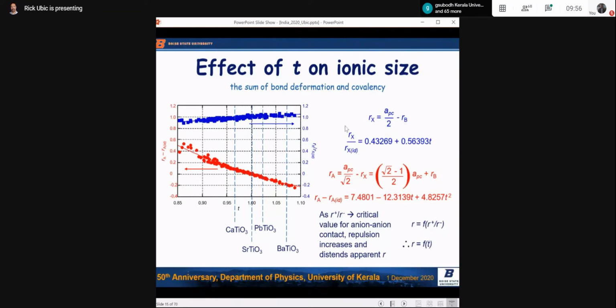And if we do that, we plot R_X from experimental lattice constant measurements, and we should get for R_X over R_X ideal for this guy here, R_X over R_X ideal. R_X ideal, remember, ideal means Shannon. So it's the Shannon size. If R_X were the Shannon size, this would just be a line here at 1. But it's not quite, it's still a line, but it has a small positive slope. And the equation that describes it is over here.